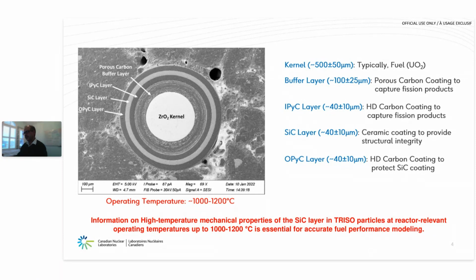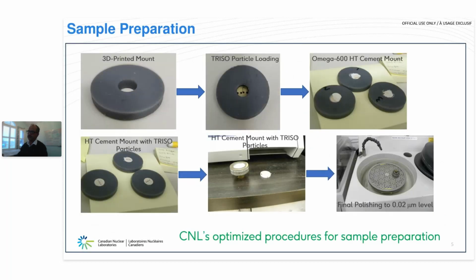Now, since these are only approximately 1 millimeter diameter particles, they're extremely small, and the problem is more complex when there will be irradiated fuel. So the normal handling of these specimens will not be possible. We are coming up with methodologies to handle both the situations. The first one here, where we are looking into unirradiated surrogate TRISO particles, we have come up with a specimen preparation method where we start with preparing a 3D printed donut-shaped mount.